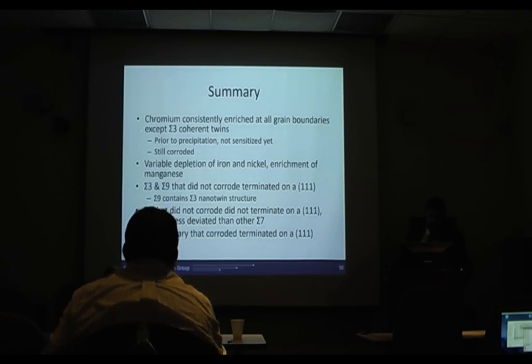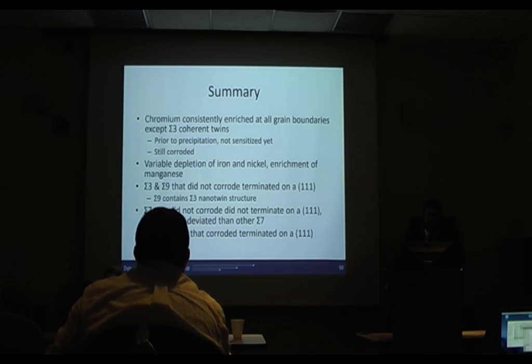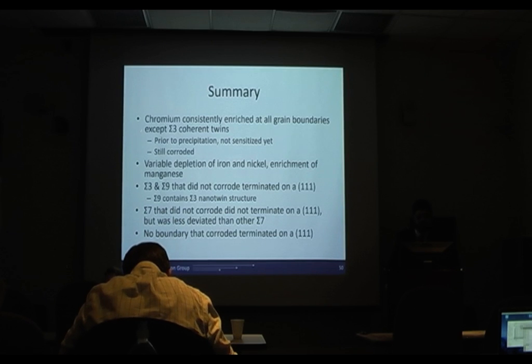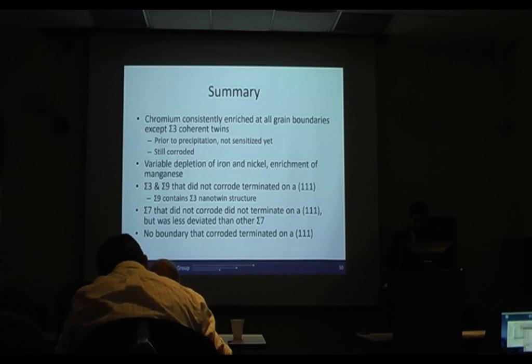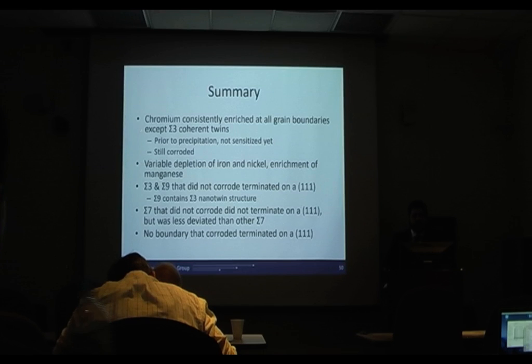We also saw some variable depletion in iron and nickel, and enrichment in manganese, but that did not appear as consistent. The sigma 3 and the sigma 9 that did not corrode both terminated on 111 grains, and the sigma 9 was actually that array of nanotwins. The sigma 7 that did not corrode did not terminate on a 111. However, it was significantly less deviated from a 111 plane than the other sigma 7, and the boundary that corroded did not terminate on a 111.